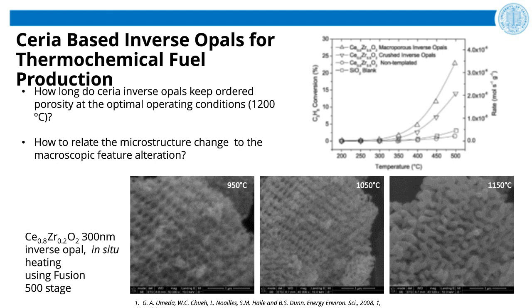This is known data, which was known before this experiment was started by Daniela. However, the biggest interest for us and for Daniela was to see how the structure behaves at much higher temperature, which is expected to give much better conversion efficiency. The temperature we needed was 1200 centigrade. However, cycling at this temperature can degrade the structure quite significantly. The question remains: how long does the ceria inverse opal keep ordered porosity under these operating conditions, and how to relate microstructure change to macroscopic feature alteration.